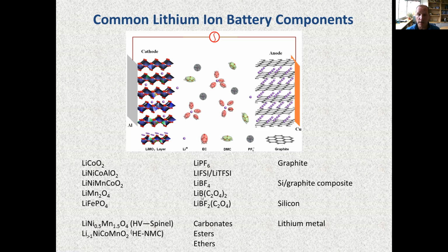Lithium bis(oxalato)borate, or LiBOB, is another salt, along with LiDFOB, or lithium difluoro(oxalato)borate. Both of these salts have at times received a lot of interest within the community. Lithium bis(oxalato)borate, LiBOB, has problems in terms of solubility of the salt. Also, it originally had some purification issues. It also produces a significant amount of carbon dioxide, which can cause gassing within the cells, which creates a problem.